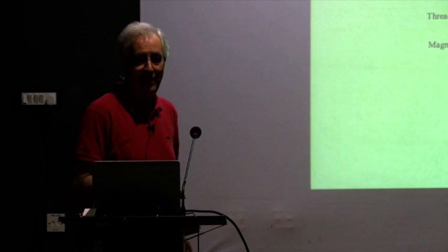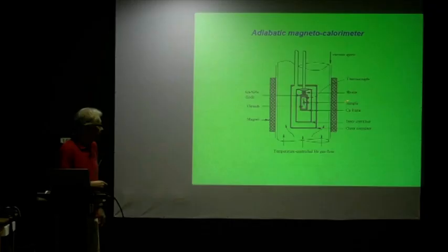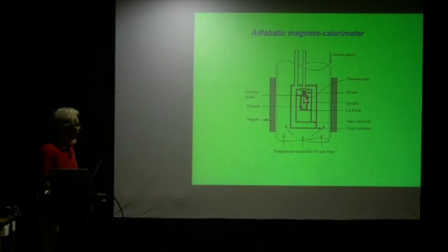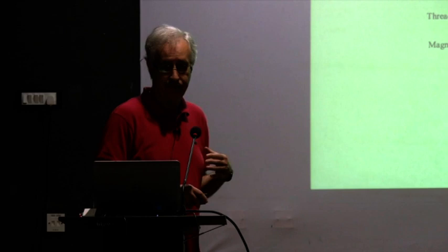Once you've done that, you have to pump out everything. You want adiabatic conditions. You don't want anything around your sample that is thermally conductive, so you don't want to lose heat. So once you have reached the measuring temperature that you want, you pump out any exchange gas that you may have introduced in here and from here also, so that your sample is now hanging in vacuum. It's in a more or less ideal adiabatic state.